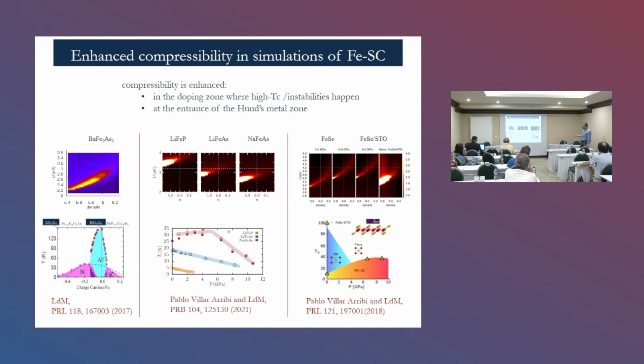So, for the iron-based superconductors, we have done several studies for the 122 families, for the 111 family, for the chalcogenides, and in all these we could, via DFT plus slave spins, show that there is a zone of phase separation, and indeed a crossover after it, dividing a zone of weakly renormalized metal from a strong coupling metal with strong orbital selective correlations, crossing the interaction doping plane in all of these materials.